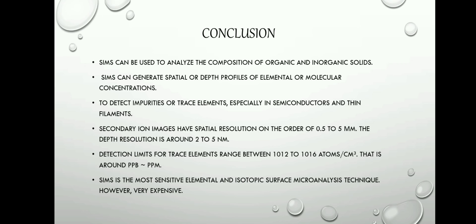Detection limits for trace elements range between 10¹² to 10¹⁶ atoms per cubic centimeter, which is around ppb to ppm. SIMS is the most sensitive elemental and isotopic surface microanalysis technique, however, it is very expensive.